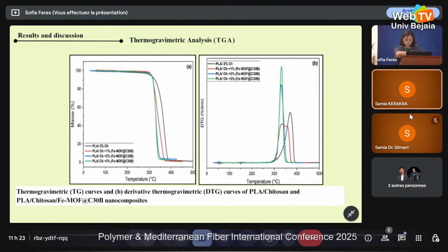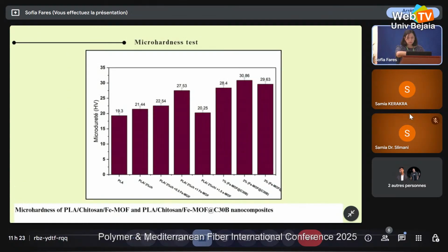Microhardness tests. As this figure shows, the microhardness of PLA-based nanocomposites improves with the iron MOF and iron MOF clay contents. The addition of these fillers enhances rigidity and overall mechanical strength of PLA. The improvement is supported by FTIR analysis showing hydrogen bonding between the matrix and fillers, which maybe enhances polymer network cohesion and mechanical properties.